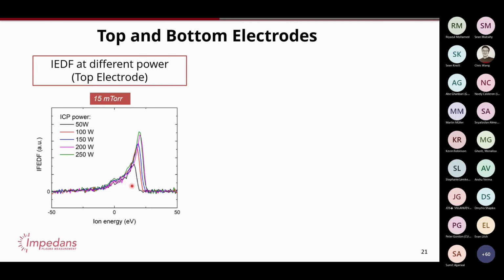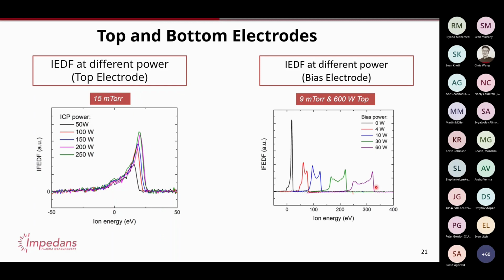But the energy doesn't increase that much. Like the energy here is going from maybe 20 to 30. So this is basically an elevation of the plasma potential. But it's not a huge increase in energy, but you get a big increase in flux. So this is why ICP tools are important. In ICP tools, you can independently control the ion flux, and then I'll show you now, independently control the ion energy.